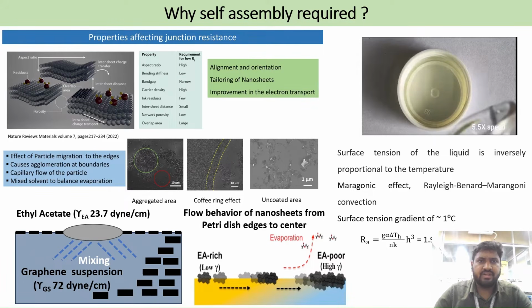To achieve the intrinsic properties of the material and to reduce the junction resistance, we need to take care of the residuals, aspect ratio, and the intersheet distance. And with conventional coatings, we see aggregation, the coffee ring effect, and uncoated areas. To avoid this, we need the self-assembly technique.